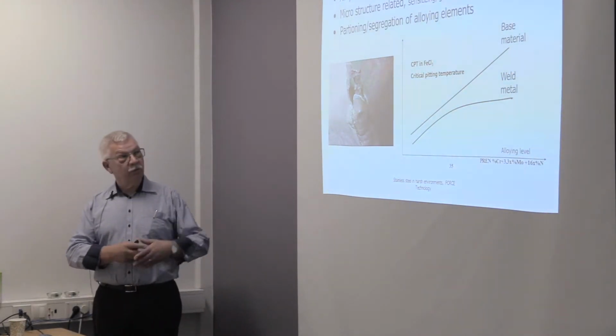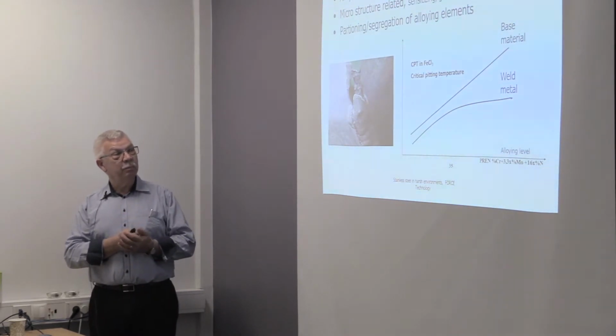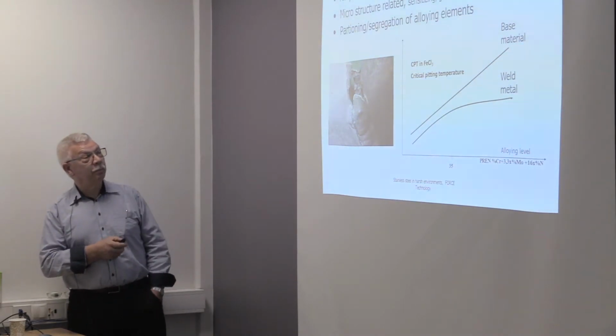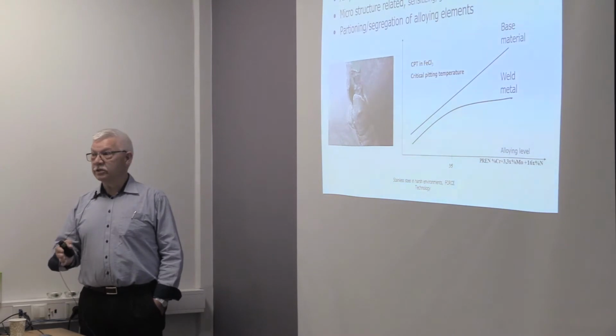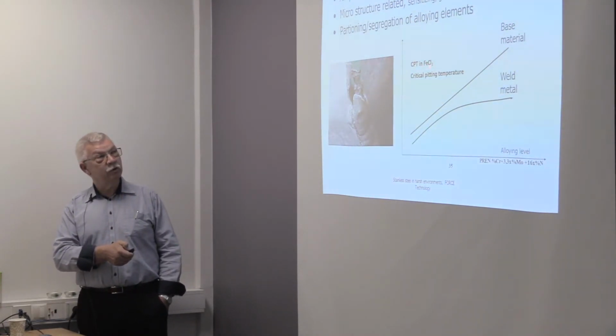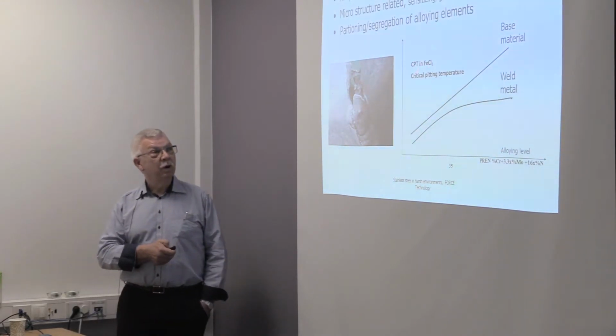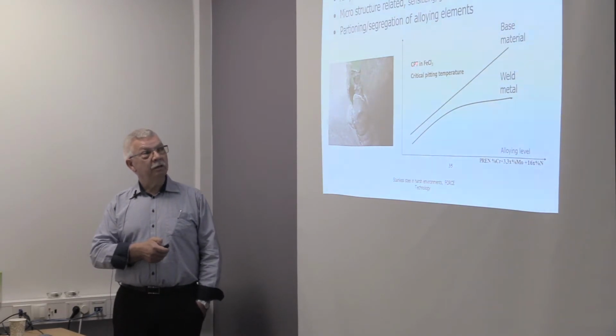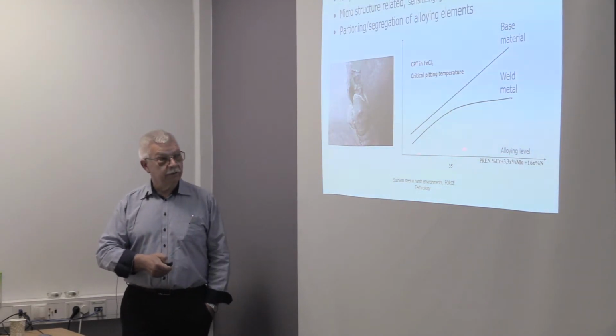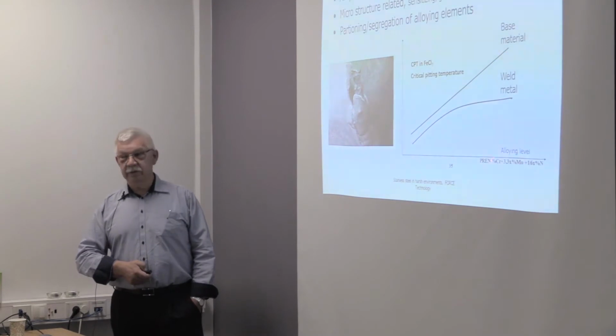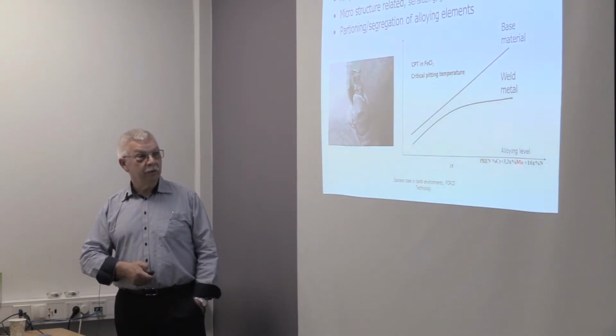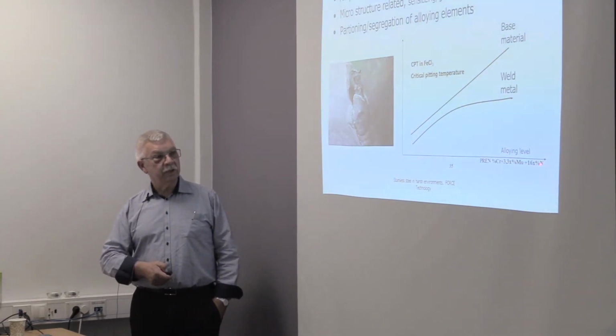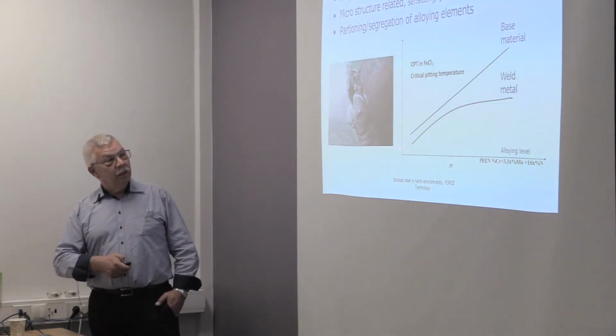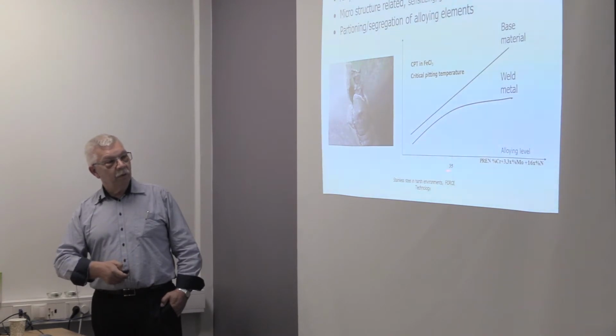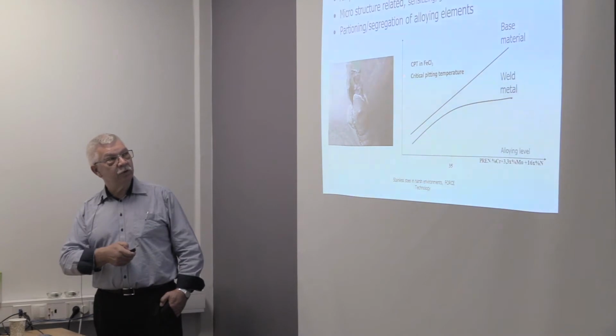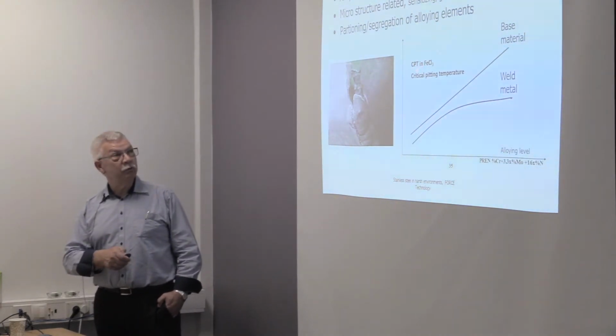One of the ways that we can quantify this is by making a corrosion test. One that is very popular to rank different stainless steels is putting them into a ferric chloride solution and measuring the temperature that you can go up to before we have pitting corrosion. And if we do this and put these results into a logarithmic diagram, we can have an equivalent for the corrosion resistance: the chromium, plus the molybdenum times 3.3, plus 16 times the nitrogen content. Then we will have a line saying that the higher the equivalent, the higher the temperature we can go to before we have pitting in this test solution.